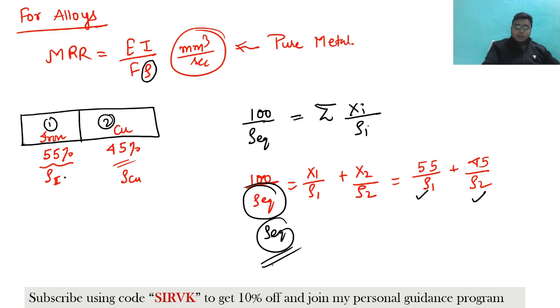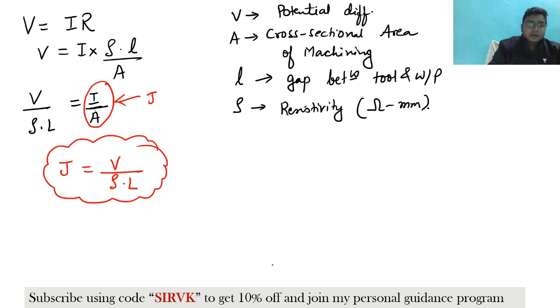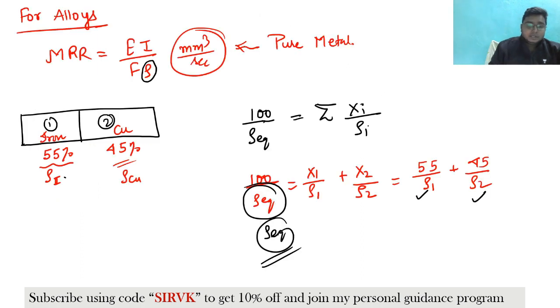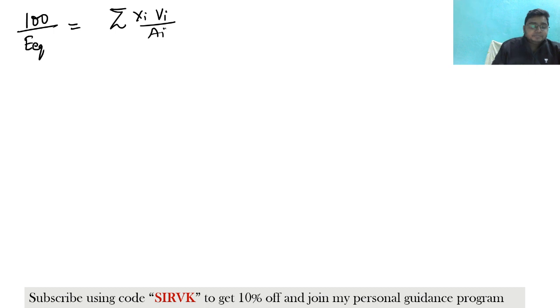Clear? Now let us talk about this E factor. Let us find this E. How can you calculate this E? So E will be calculated by 100 by E equivalent is equal to summation of xi into vi by ai. Clear? Now what is this x? This x we have seen is the proportion or percentage of material.